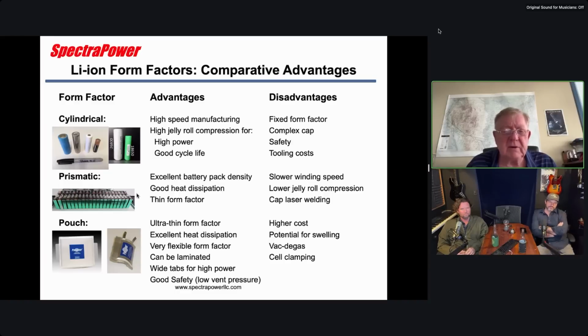Prismatics, so you get battery pack density. That's like we were just talking about there, you can see. Heat dissipation is better because it's a flatter form factor. That's one of the problems when you have a very big cylinder. It's getting the heat out. From a thermal perspective, if you think about it, the jelly roll has wound plastic sheet, which doesn't conduct heat, and the electrolyte acts more like almost an oil in terms of impeding heat transfer. So when Apple first went to some bigger cells, this 26650 back in the day, they had cells exploding because Sony hadn't really quite figured out the heat dissipation in the large cells.